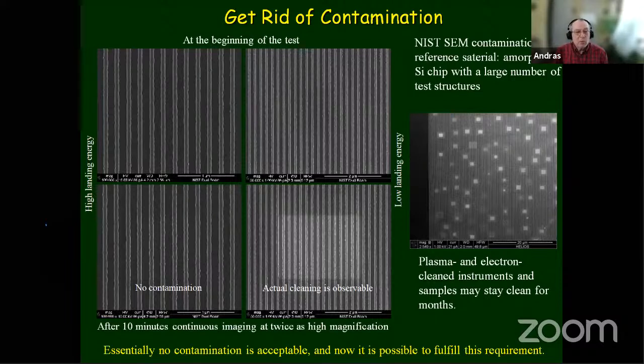This is especially at low kV, because you have a lot of secondary electrons close to the surface at low energies. So it is possible to have an SEM so clean that for a month, you don't need to clean it again, and you can dwell on the sample as long as you wish. If you want hours, you will not have any carbonaceous contamination. The next slide, please.